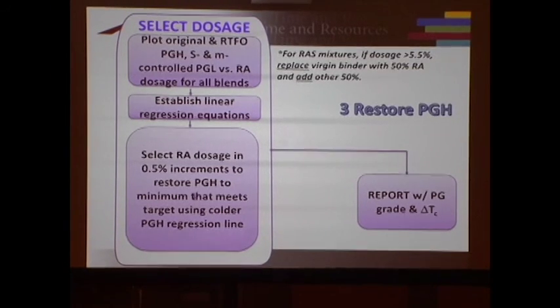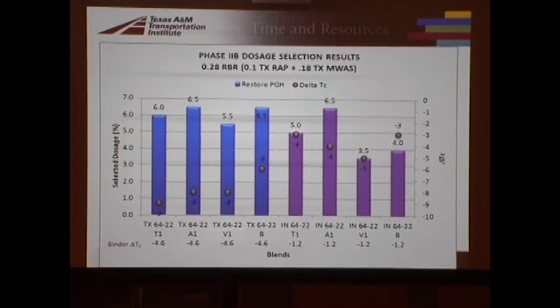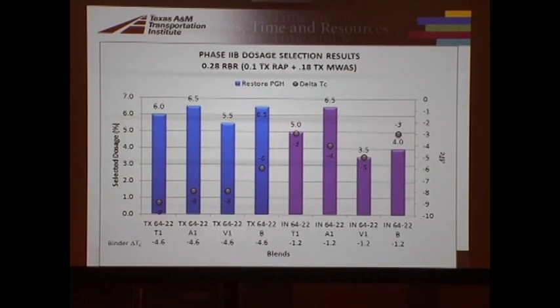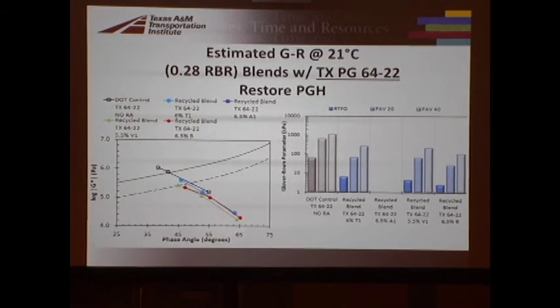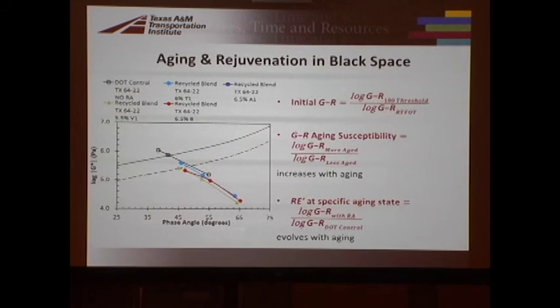And so we're going to restore the high temperature grade. When we restore the high temperature grade, we get a dosage that's between that 3.5 and 6.5, right? So that's kind of where we want to be. And when we do that, it looks like this in black space. It's not nearly as over-softened as it was before. And we did check it in Hamburg. In Hamburg, we really couldn't separate out moisture and rutting effects, so we did a dry Hamburg, and in dry Hamburg, it passes. So we think this might be the right approach, this restore the PG high temperature grade.